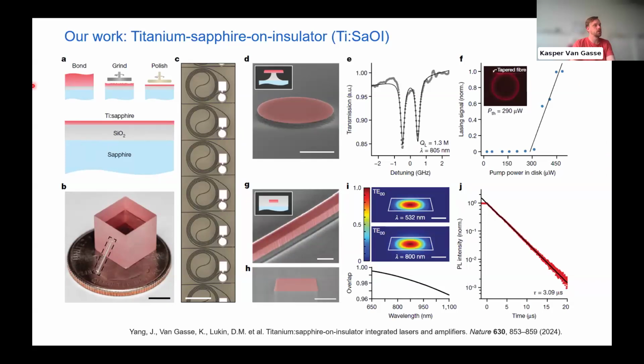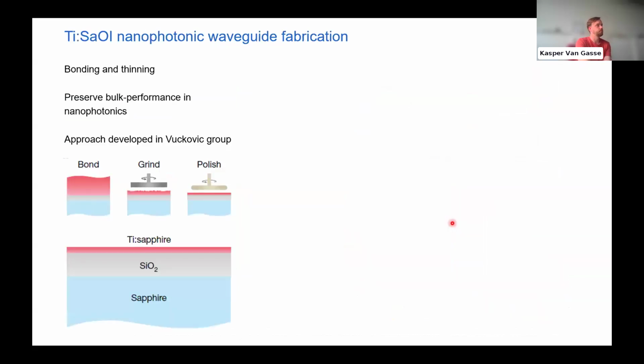But here you can already see a bit of the overview of the platform that we made. It's a nanophotonic platform that's made by bonding, grinding, and polishing crystals, not by smart cut or deposition. And here you can see, for example, a microscope image of several titanium sapphire tunable lasers. We also made a little micro disk here with a Q factor of about 1.3 million that showed extremely low lasing threshold. We have made some nanophotonic waveguides, and I'll go into a bit more detail.